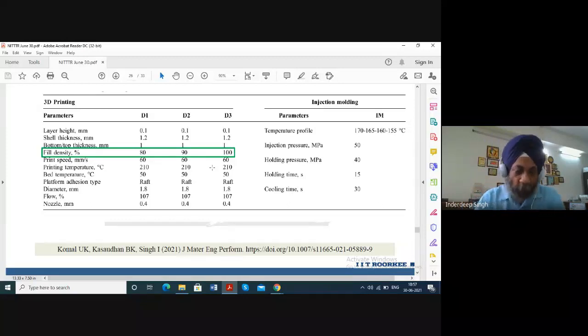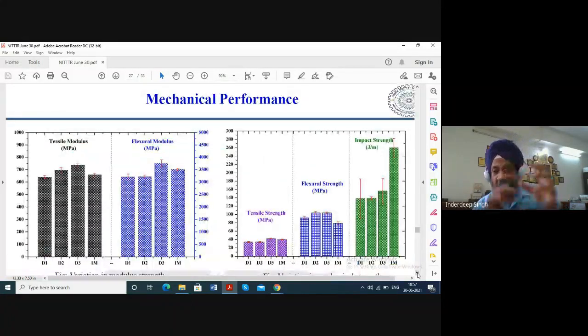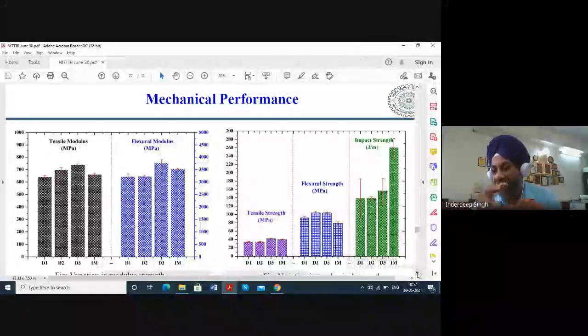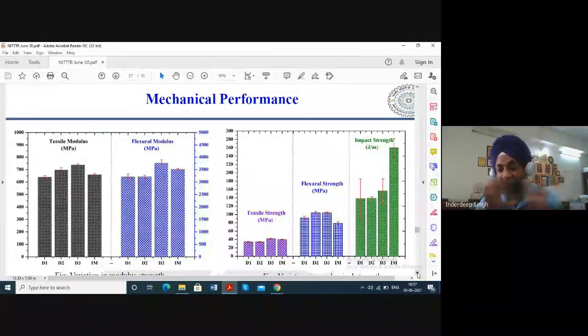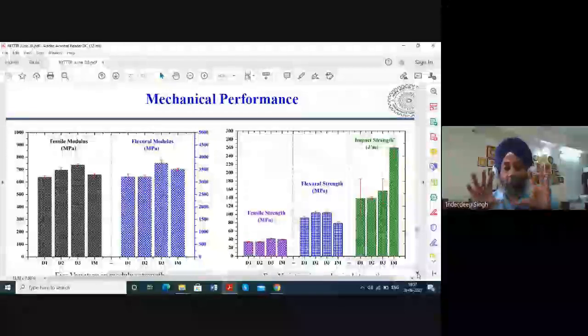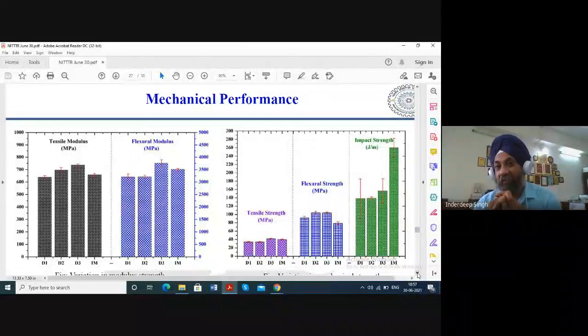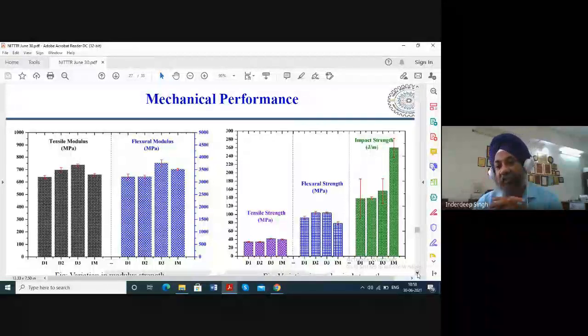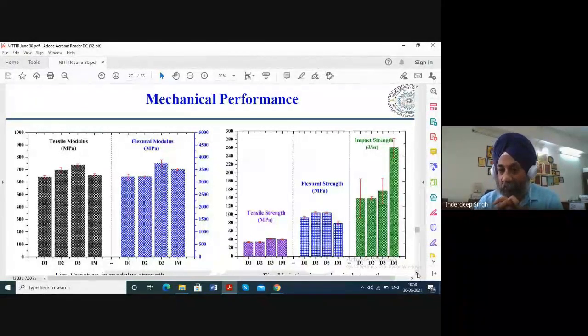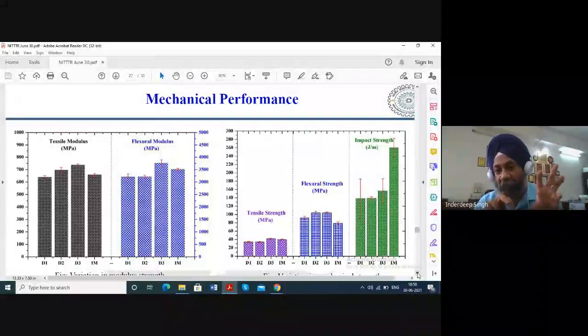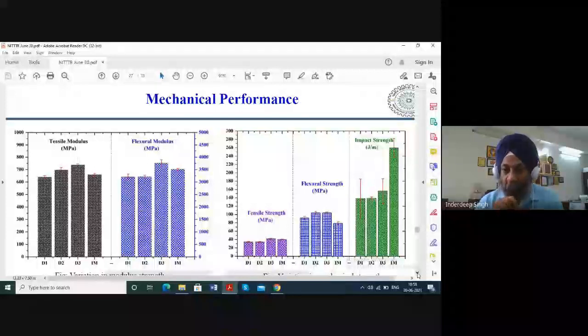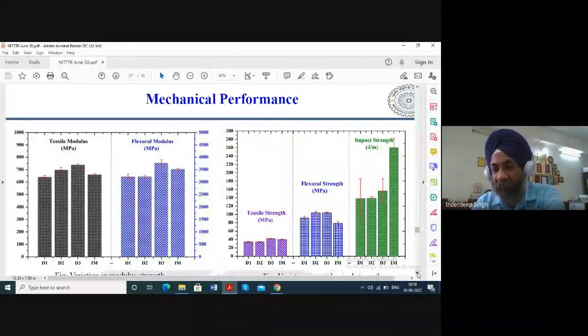the material being PLA. So now here, another research direction that we have got after this analysis is that the impact strength also needs to be optimized, that these parameters may slightly change, so that we are able to have a trade-off between the tensile, flexural and impact strength. But the main point that we are trying to address here is that the properties are more or less comparable. There is not a very large difference in the properties, specifically the tensile and the flexural properties of the parts made by the FDM process and made by the injection molding process. Further, maybe research is a continuous process. Further efforts can be put in this direction.